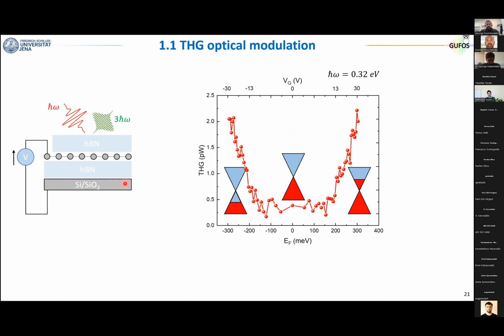You see now the silicon dioxide is much thinner, it's 90 nanometers. So here we apply gate voltages of around plus minus 30. The graphene is encapsulated, so at 0 gate voltage the Fermi energy lies at the Dirac point, the material is undoped. And now you see this curve that I like very much, it's very beautiful in my opinion, where we can see the enhancement in the third harmonic. There is no pump pulse, this is only gate tunability, but now the enhancement can occur symmetrically in the p-doped and n-doped region.